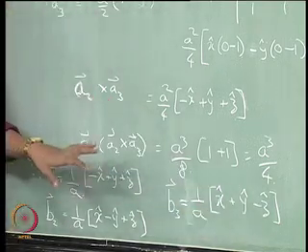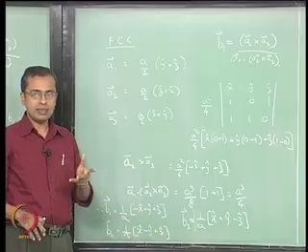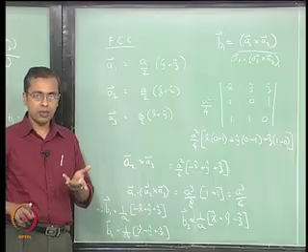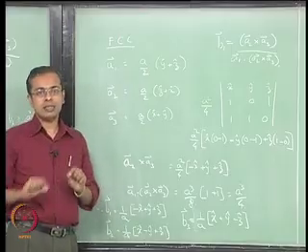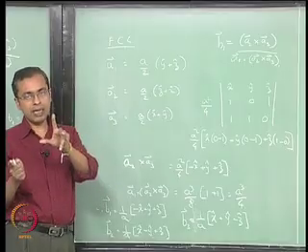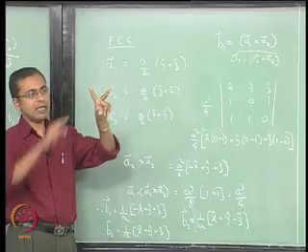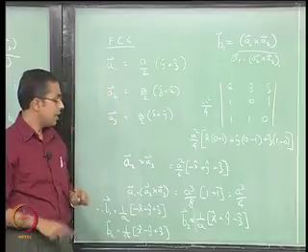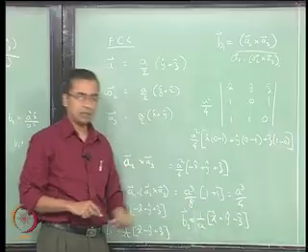In fact, if you make a plot of this, you will find that it is the same as a body centered cube, wherein these are vectors going from the origin to the 3 body centers. Okay, so to 3 neighboring body centers is where it is headed. So that is how we are getting the 3 body centers, and then you can build your structure around it. Right now you have to just take my word for it, but if you just plot it, you will find it.